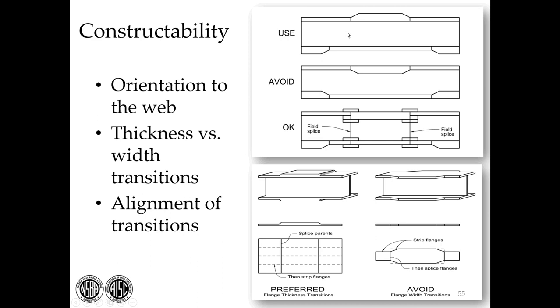Through the manual, we talk about how to do flange transitions. Most people are well aware that if you have different thicknesses, you should show them to the outside, not to the inside. Although, if you have some rather long spans and you want to have thicknesses to the inside, you can do that readily if you make them only at field splices. So you see here a field splice and a thicker flange at this location, but no transition. So each individual girder has the same depth. So that's okay. And in fact, this was used on the Tappan Zee bridge replacement very effectively, which they intended because they wanted a flatter top surface for deck panels.